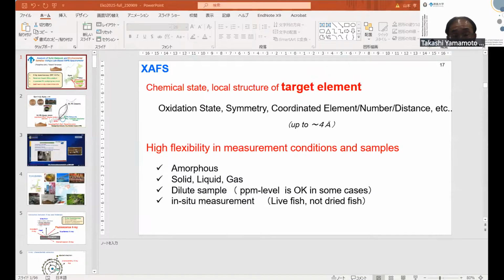We can obtain information about the chemical state and local structures: the oxidation state, the symmetry and coordination environment, the kinds of neighboring elements, and the numbers or distances. The difference between XRD and XAFS is that with XAFS we can know the information about the local structure up to maybe 4 angstrom, one or two coordination spheres. Long range structural ordering is not needed.